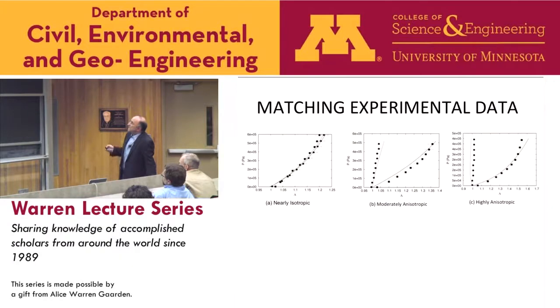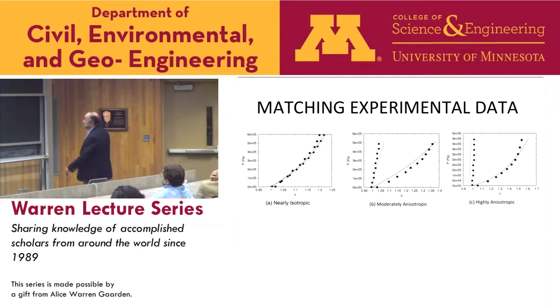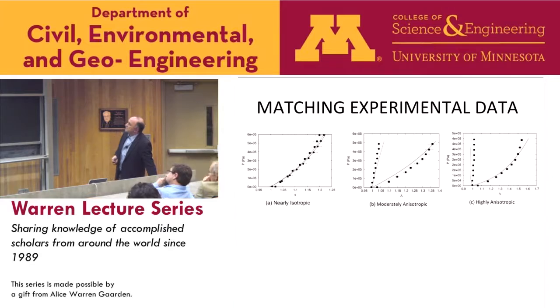So here's the matching, right? The solid lines were experimental data. These were the best fit experimental things. From computations, right? The points, right? You see some standard deviations on this. Now, the interesting thing about this plot is that in each case, we used different material properties. We couldn't fit it with one property. The properties were not dramatically different from realization to realization, but they were like 20–30% different, right?